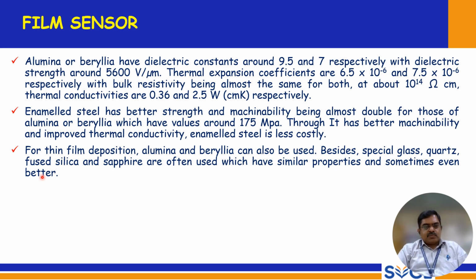So here the alumina and beryllia have dielectric constants around 9.5 and 7 respectively, with the dielectric strength around 5600 volts per micrometer. Thermal expansion coefficients are 6.5 × 10^-6 and 7.5 × 10^-6 respectively, with bulk resistivity being almost the same for both at about 10^14 ohm-centimeters. So thermal conductivities are 0.36 and 2.5 watts respectively.